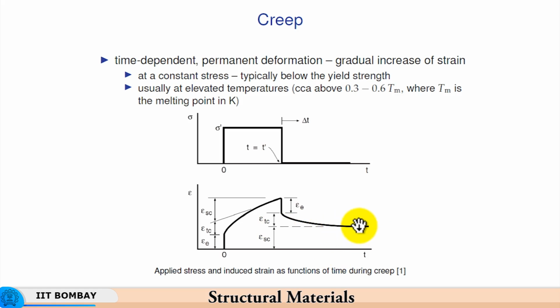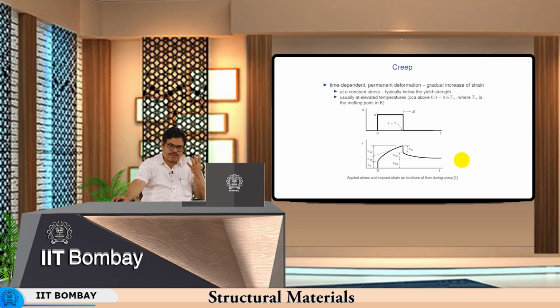So, although the yield point has not been crossed, although there is no plasticity as such which might be involved, still you have creep, meaning a creep strain remaining behind in the product. So, that is something we need to guard against. For example, you have certain tolerances given for certain dimensions, and because of creep over a period of time these dimensions get distorted or increase. There is a strain in the component. Then as a result of that creep strain, the component has to be replaced because it is no longer able to function the same way as it should have functioned, or the same way as it is designed to function.